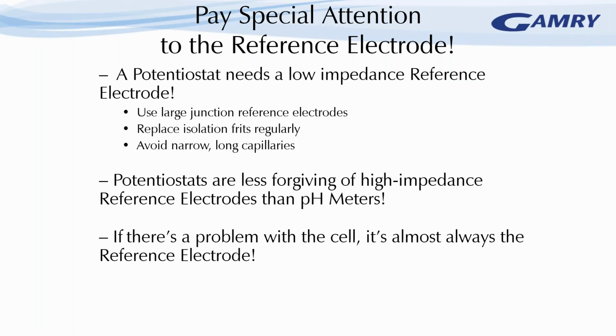Potentiostats are much less forgiving of the high impedance reference electrodes that you can buy than the ones used for pH meters. The reason is that to control the potential, we need a fast moving circuit that can adjust the potential in very small increments. And often when you find there's a problem with the working of your potentiostat, and it's in the cell, it's often due to the reference electrode.